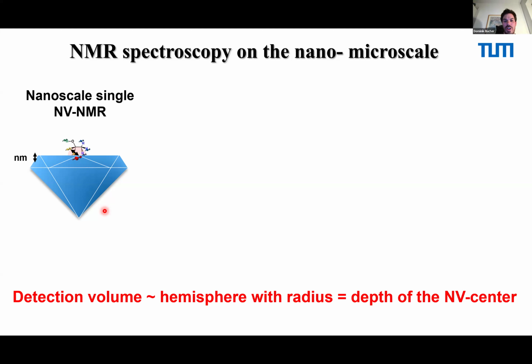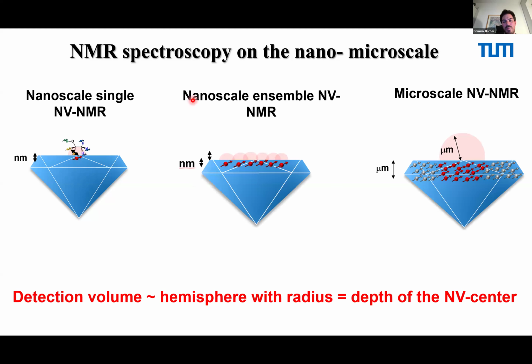Okay, and we now distinguish single nanoscale NV NMR. The next one, which is what we mainly do in my lab, is nanoscale ensemble NV NMR. So we take many NV centers which are close to the surface. It's again nanoscale because each of these NV centers has its nanoscale detection volume. And then the third one, which we categorize, is a couple of micrometer thick layer, and the same rule roughly applies. We then go to this micrometer volume.